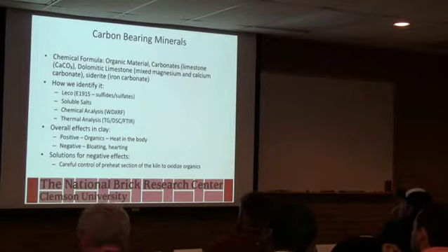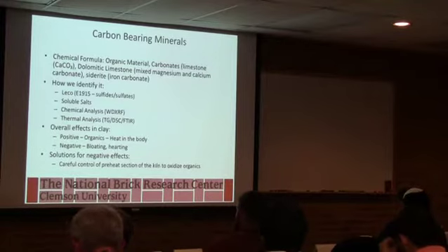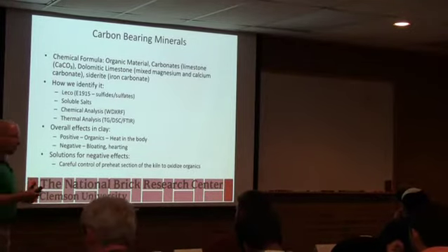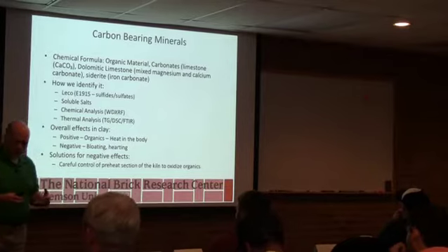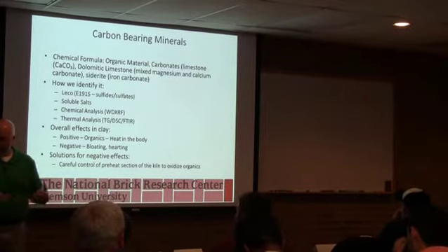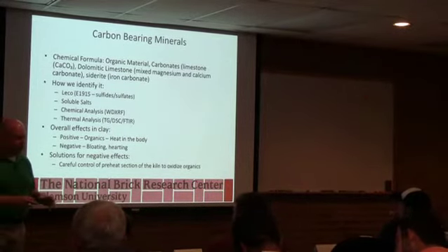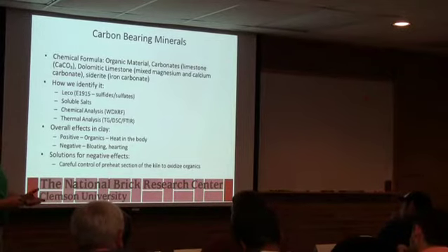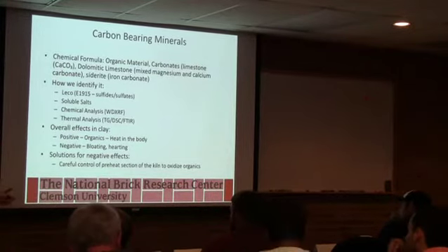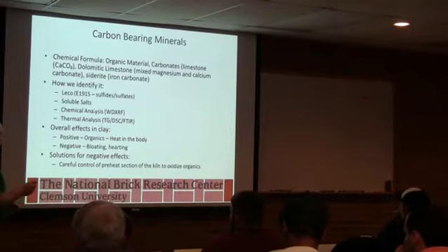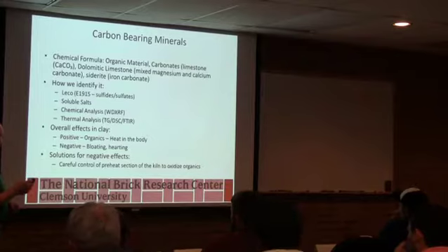So carbon can come in a lot of forms. Everything has some organic carbon. Our materials are materials that have been weathered and typically transported by water to the point where we mine them. And along the way they pick up all kinds of contamination. Could be dead leaves, dead animal, whatever. And it leaves some organic material in there that has to burn out. That's usually in the early preheat. And if you don't get that out, it can lead to coring or things like that, or bloating.